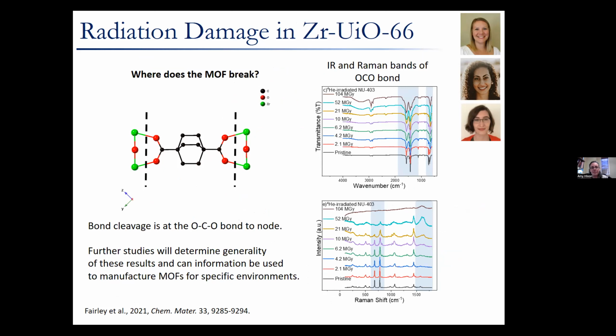Further analysis of these irradiated materials by IR and Raman spectroscopy allowed us to understand where the MOF is actually breaking. Is it breaking at the node itself? Is it the linker that's decomposing, or what? The areas that are highlighted in blue tell us that the bond cleavage is at the bond between the linker and the node. And so that is where the MOF is most susceptible to damage. This allows us to understand whether we can specifically tailor or design and synthesize new MOFs that won't have this drawback or susceptibility in the radiation fields. And also whether this is specific just to the zirconium UiO-66 MOF or to MOFs in general.